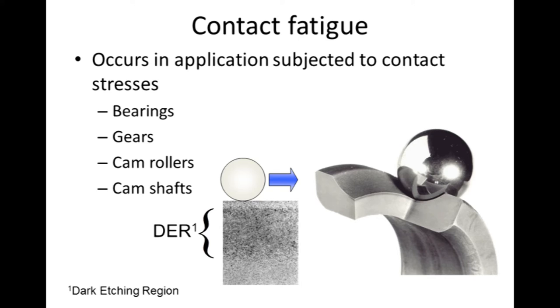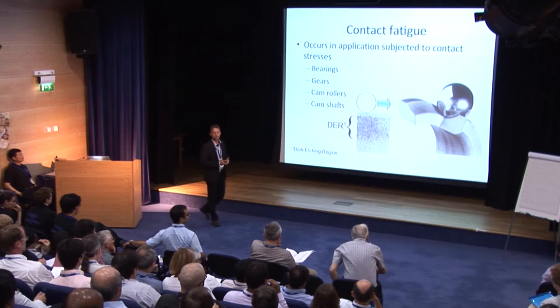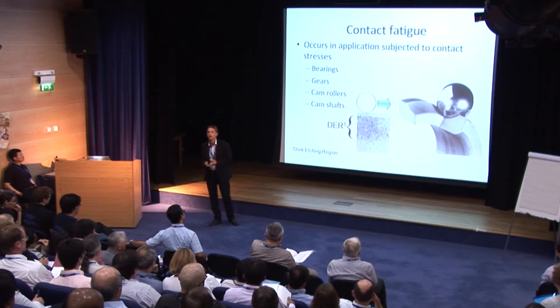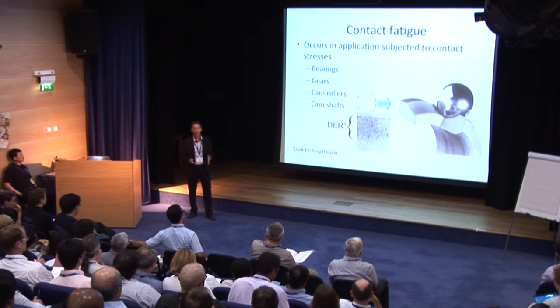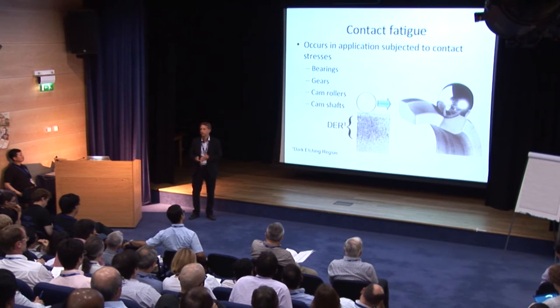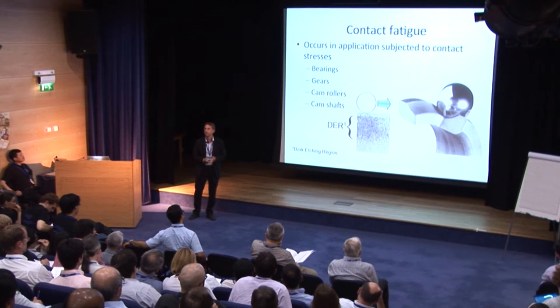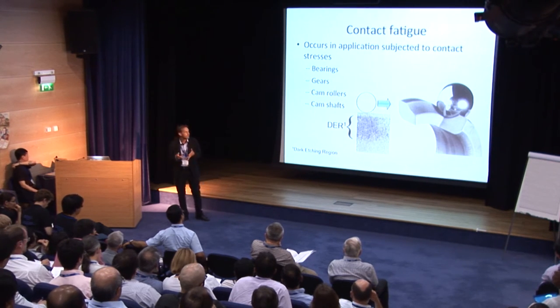And what do you see when you make a rolling contact fatigue test? Now we see something underneath the rolling raceway. We develop what we call the dark etching region, which is well accepted. We know it's there. But what is it? This is really the starting point for fatigue. And I think we have been relying very much on fracture mechanics when it comes to fatigue. That means we are trying to calculate the fatigue without knowing the cause of the initiation. And I think what we should investigate more is really the initiation stage.